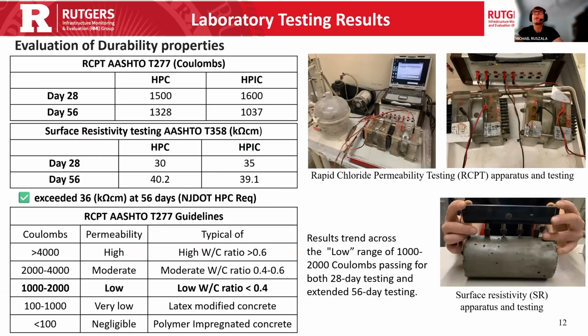Regarding durability properties, we tested RCPT, so that's rapid chloride penetration test, as well as surface resistivity. For both of these tests, all the materials ranked in the low category, so that indicates a very dense matrix and a durable material. And this is typical of HPCs with this water cement ratio.